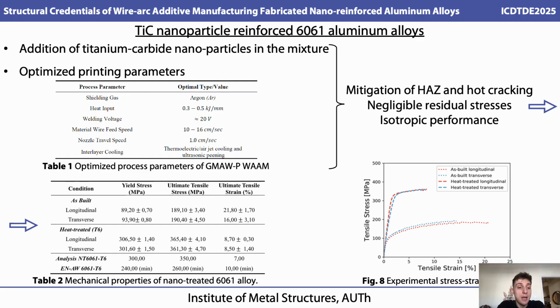As you can see in table 2, these are the mechanical properties of nano-treated 6061 aluminum alloys. As you can see, we get literally almost no anisotropy on the mechanical properties, and compared to typical 6061-T6 heat-treated aluminum alloy, we have significantly improved mechanical properties. Yield stress and ultimate stress are both increased, to 300 megapascals and 350 megapascals, compared to 240 and 260 megapascals for typical 6061-T6 aluminum alloy. These are the experimental stress strain curves based on available literature, and we will use these values for the analysis to be conducted at the following stages.